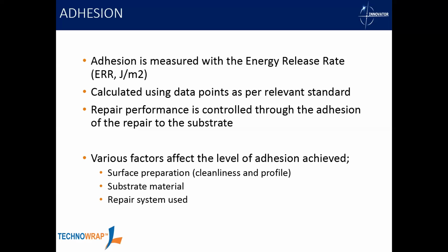Another one is the actual substrate material itself. So is it carbon steel we're repairing? Is it stainless steel? Is it copper-nickel? Is it a duplex steel? We bond differently to all of those different materials. And then just to add in a few more options, every repair system we have bonds differently as well. So the fiberglass will bond differently to the carbon fiber products. So there's quite a few variables again there.